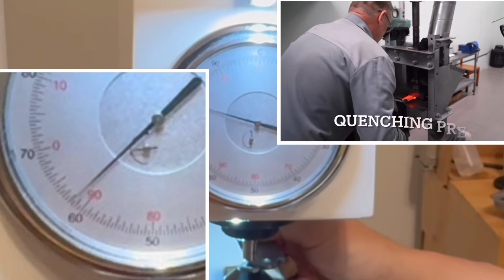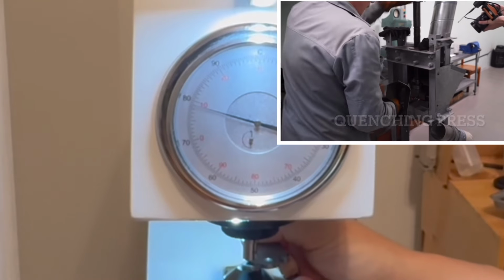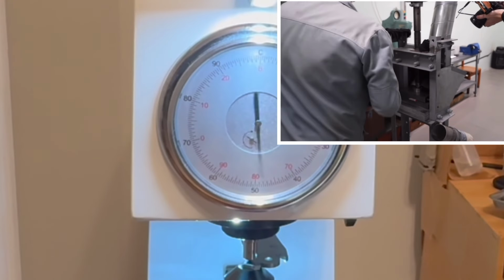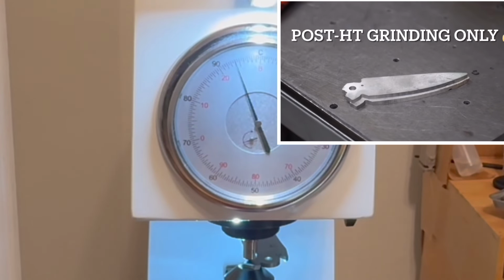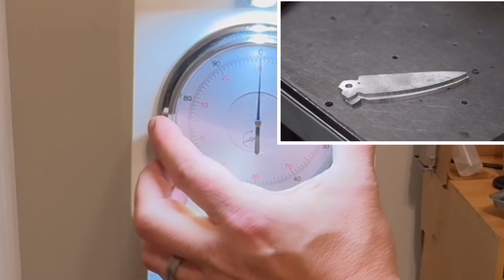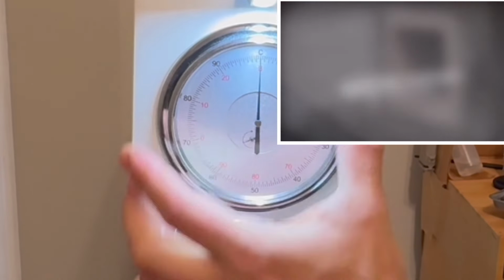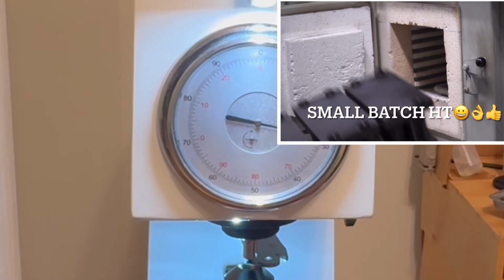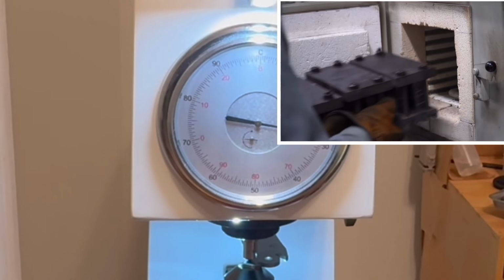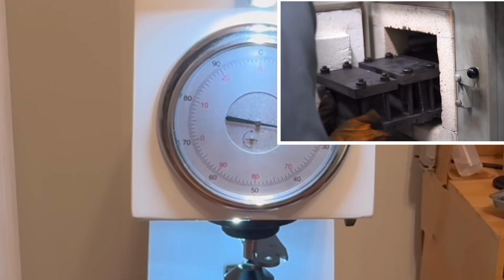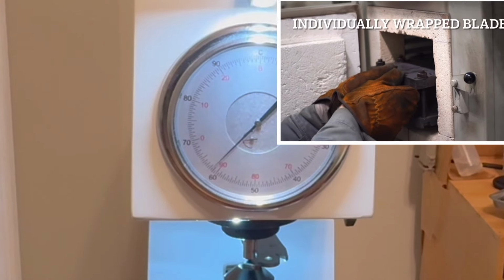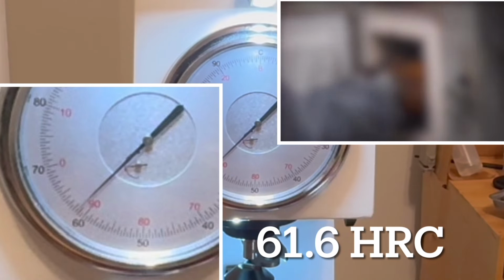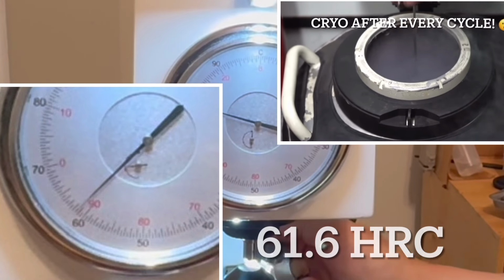Check the timestamp where I predicted the hardness. Very proud of myself here. Anyway, setting up for the second poke. In the video, you can see that they don't use an atmospheric oven. Instead, they pack the blades into stainless foil, and then, don't laugh, they add a piece of newspaper inside with the foil to burn out any oxygen. 61.6 HRC on the second poke.